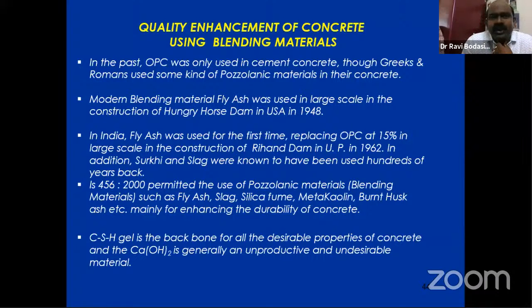So these are the quality enhancements of using blended materials. In the past, only ordinary Portland cement, OPC, was used, but in modern buildings, fly ash, GGBS and micro silica, which are called mineral admixtures, can be used. We discussed the free lime, the leaching effect, the calcium hydroxide which is untreated. This calcium hydroxide again reacts with pozzolana material like GGBS. GGBS is nothing but ground granulated blast furnace slag, and fly ash is a byproduct from any thermal power plant by burning coal. The GGBS is a byproduct from steel. So by utilizing these byproducts, we have an advantage of the eco-friendly and green building concept.